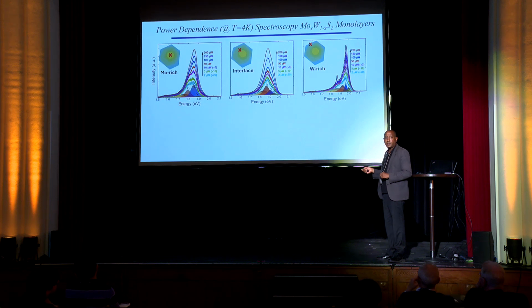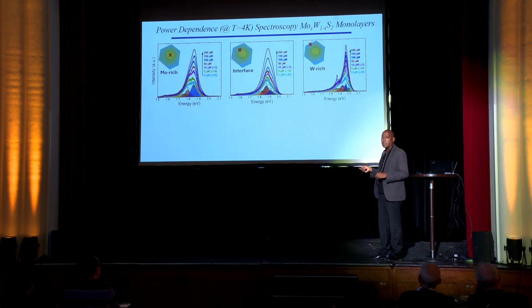We use pseudo-Voigt functions, and we identify that 6 peaks can fit any of these spectra nicely. And that means that there are 6 peaks to assign for each of these spectra. Not only that, you also have to do that from the center all the way to the edge.